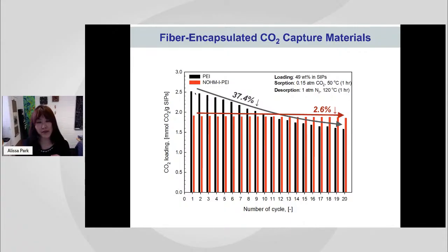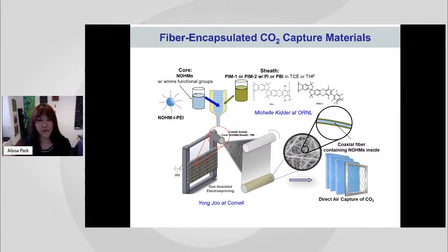So for the next generation of CO2 capture materials based on NOHMs, we started thinking about another set of form factors. This is the fiber encapsulated CO2 capture material we developed working with Michelle Kidder at Oak Ridge National Lab and Yong Joo at Cornell University. Basically, we mixed our core material NOHMs, which really captures CO2, with a shell material that has really good permeability of CO2 through the system, but if we can, also selectively rejects the water. Wouldn't it be great? So we selected a polymer called PIM for that purpose.